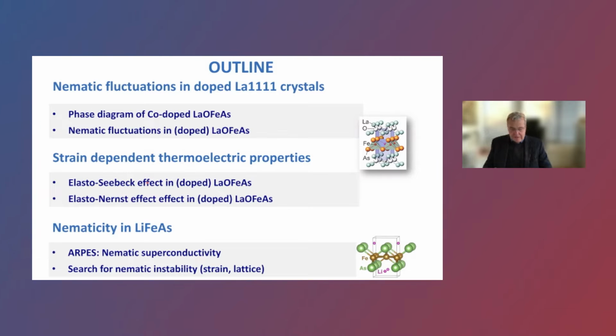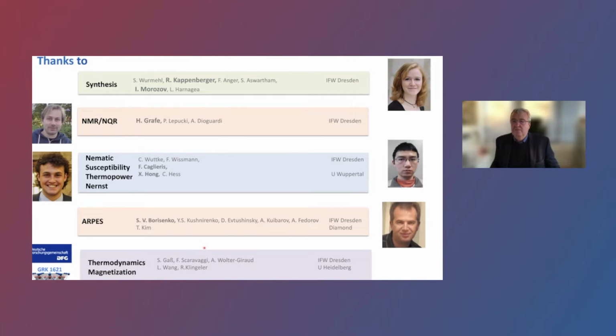And then if time allows, I will continue and will show you also recent results on lithium iron arsenide, which is a very peculiar, very nice system on the one hand, because it allows very detailed studies of surface science, so photoemission and STM studies. But on the other hand, it's really very much different from the other iron-based superconductors, also with respect to the phase diagram and the properties, and this I will discuss. And I will in particular discuss here evidence for nematicity, which is very much different from that what we found in other systems.